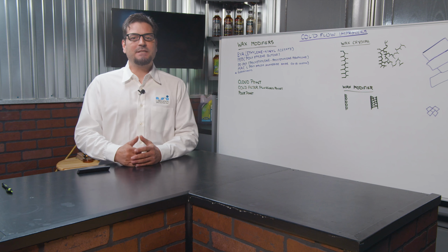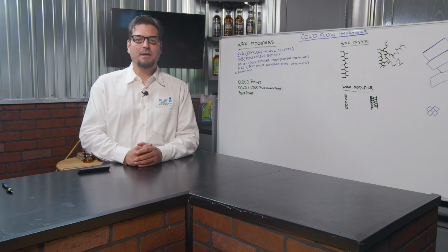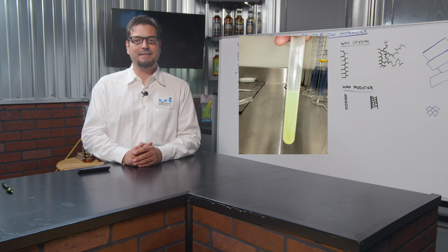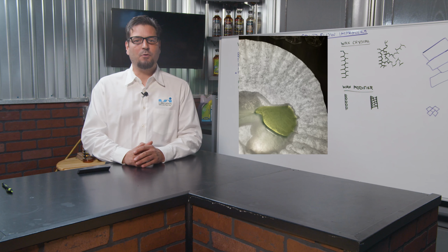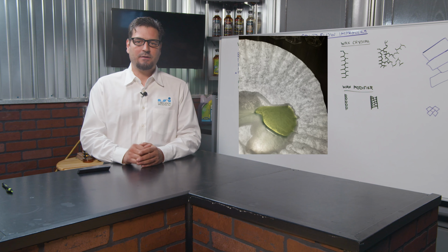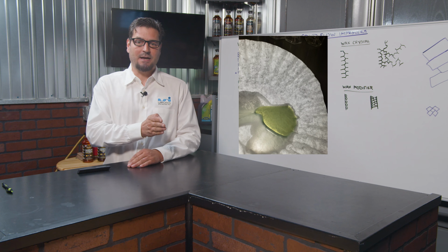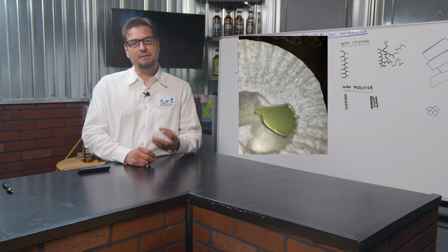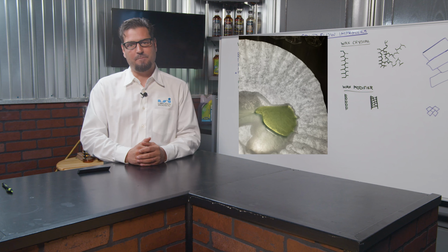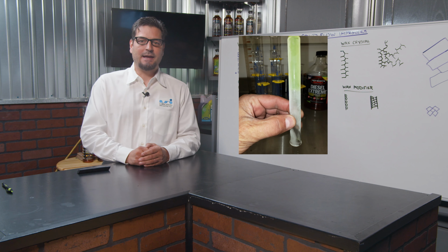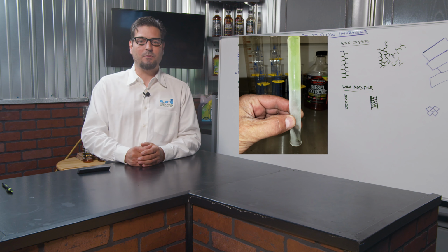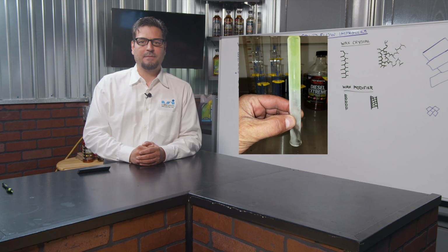You never know. We test cold flow properties from 3 different methods. Number 1 is the cloud point, ASTM method D2500. This is the point where the wax crystals start to form and you will see a cloudiness in the fuel. The second is the cold filter plugging point, ASTM method D6371. This is where the flow of the fuel will actually be stopped because it gets caught in your filter. This is the size of the crystals that are big enough to get caught, and the amount. The third one is the pour point, which is exactly like it sounds. ASTM method D97 is the point in where the fuel will not pour and become a solid.